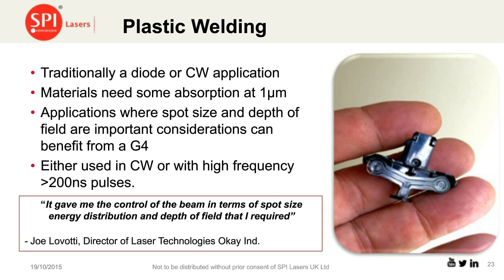At last, we get onto the welding side. So we'll start off with plastic welding. Traditionally, this is a diode or a CW application. The materials, for solid-state lasers, need to absorb at 1 micron. As I said, typically a fiber laser or even a nanosecond laser wouldn't be considered for these applications. There are easier ways to do this, possibly. But there are certain applications where spot size and depth of field are important considerations, and that's when the benefits of a fiber laser can come in.